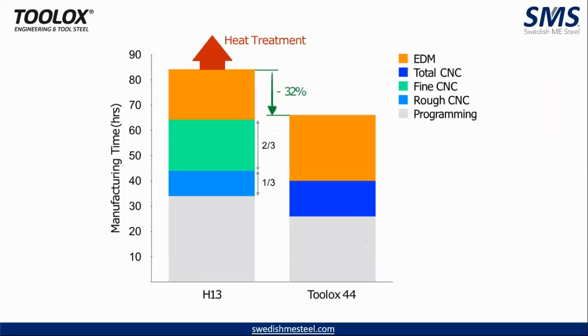So this we have made for an annealed hot working steel. I think there shouldn't be any major difference with cold working steel also. So what we say here is, when you use Toolox 44, which is a pre-hardened material that we are discussing here, when you compare with any annealed material, D2 for example, there is no requirement for you to do two-time machining at annealed condition as well as after heat treatment. There is no two-time programming which is required.